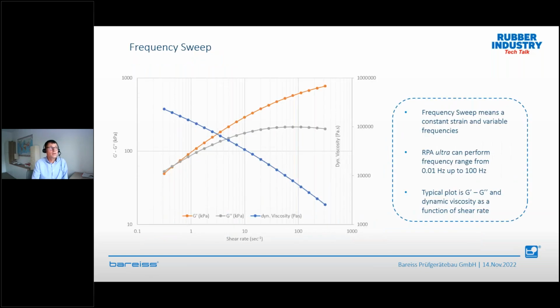So going the next step, going back to processability, going back to viscosity. We discussed kinetics, the chemical behavior of your compound. Now we're going back and want to look at the physical properties, meaning a frequency sweep. What is a frequency sweep? A frequency sweep means a constant strain, for example, 0.5 degree of arc, and what we have is variable frequencies.